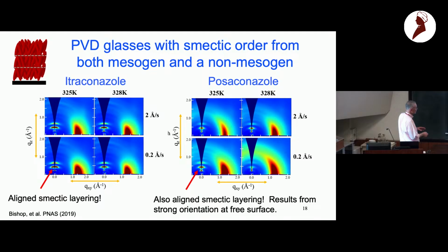And I think this is already pretty amazing that you do nothing more than throw molecules down on a surface in a vacuum, and they achieve this beautiful packing, which is indicated. These diffraction lines here tell you about this spacing, and as I mentioned, this is telling you about the vertical orientation. So that's cool. And you can do this on a wafer as big as you like. So everywhere on the sample, you're getting this orientation.